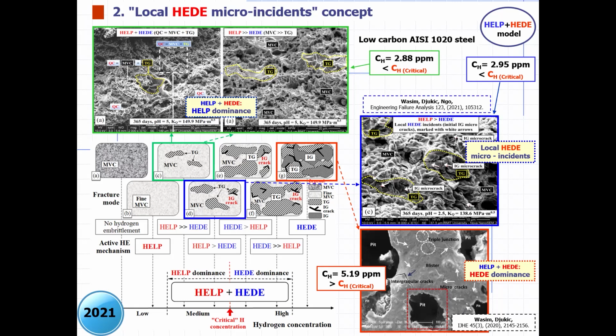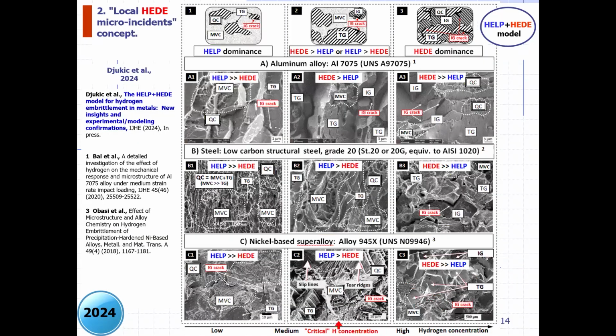I don't have time to explain the HELP and HEDE model mechanisms, but they are very well known in the literature. So here is the overview that we have very similar fracture appearance in low carbon steel, in nickel-based superalloy, and in aluminum alloy. As you can see, we have a transition between mechanisms manifested by typical ductile failure, then a combination of ductile-brittle behavior of the material, and then transition to full brittle behavior manifested by intergranular and transgranular cracks, which is a true confirmation of HEDE dominance and accumulation of large enough HEDE micro-incidents, which we have at a relatively low hydrogen concentration.